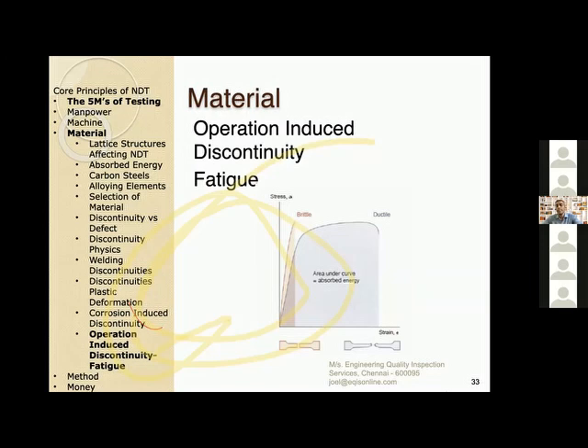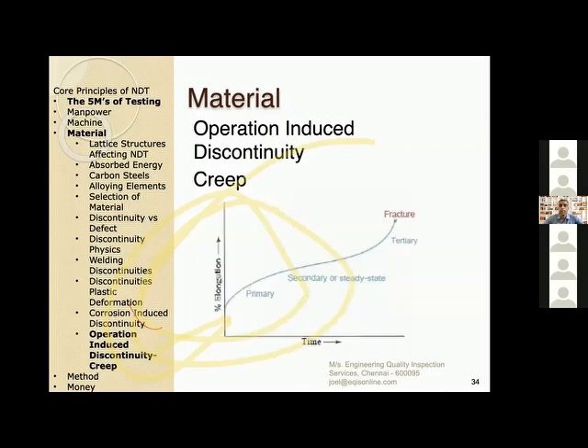So this kind of a defect can easily be seen when we do a tensile testing, where if a material is really stressed out, it is going to try its level best to stick on, but at one point it will break and it will have some edgy defects. Whereas if a material is very brittle, it's going to break like a biscuit, then the fracture specimen will have very smooth edges and it will almost look like it's broken like a biscuit, as an example. So this is where fatigue plays in. And similarly, creep is like I'm slowly giving it a permanent load, which is developing in its primary, secondary, and tertiary stage until it finally fractures.